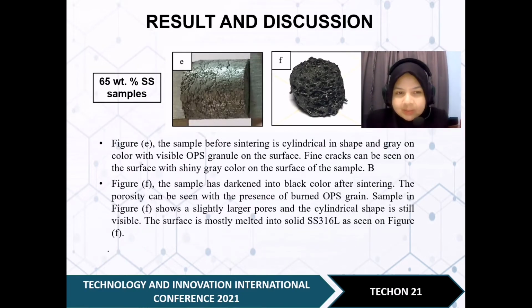The next sample, we increase the stainless steel by another 5%. In this sample, we can see cracks happen. Whenever we increase the stainless steel content, the cracks happen more and more. We can see the cracks clearly in this picture compared to the previous samples.